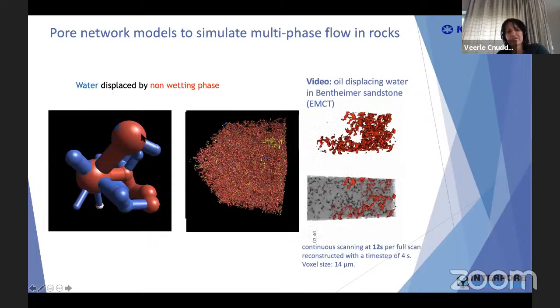So what you have is the rock fully water saturated in blue in the model, and then we inject a non-wetting phase coming from the right towards the left, shown in red. We model this, but we also validate the model by doing CT scans.